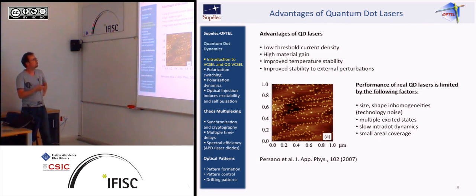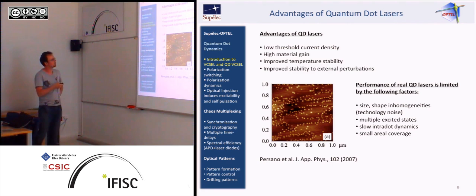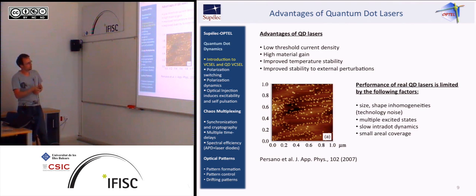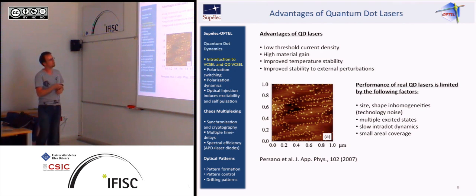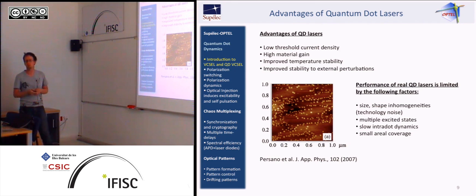It has been proved, or studied recently also, that they might bring quite a lot of improvement in temperature stability and also in robustness to external perturbations like optical feedback, for different reasons. However, the performance today is strongly limited by the technology, because if you grow these things artificially on top of a wetting layer or inside a superlattice, basically you don't control much the number of dots, the size of the dots, or the homogeneity of the dots.